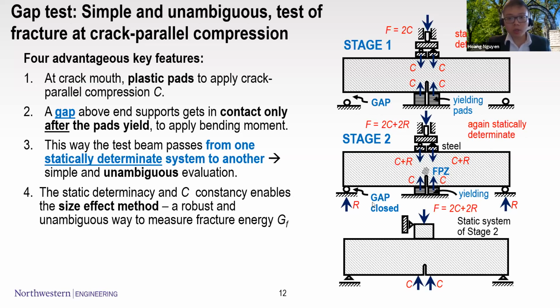However, after a while, the gap will close while the crack-parallel stress from the pad is still applied, and the bending moment that can trigger the crack starts to apply at the support. Later, at the crack tip, it will be subjected to both tension for the crack and also compression from the crack-parallel stress. So the beam is hypothetically transformed from one statically determinate system to another statically determinate system. And because of the constancy of the crack-parallel stress, we can use it along with the size effect method, which I will mention later, to extract the fracture energy.